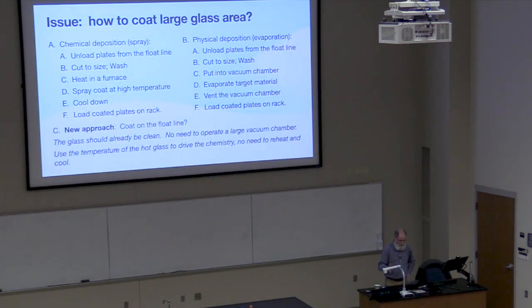So somebody came up with the idea, why don't we coat the glass right on the float line, right? So the glass should already be clean. If you coat it right after it's formed, it's clean, or so we thought. You don't need a vacuum chamber, and you can use the temperature of the hot glass to drive the chemistry. So no need to reheat the glass, coat it, and cool it down. Just coat it when it's hot the first time. You can imagine that would seem to be a better energy approach.